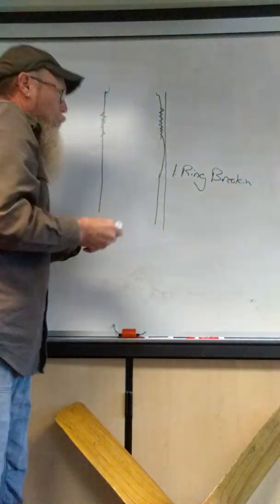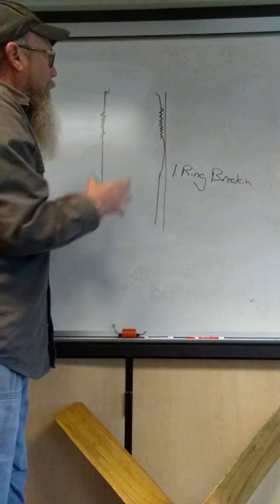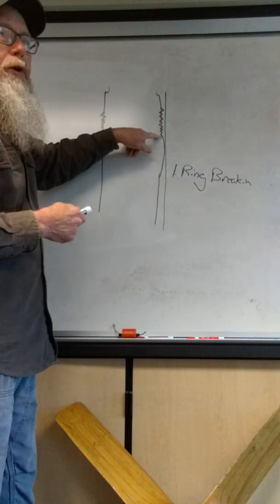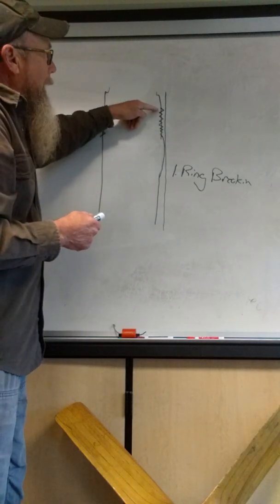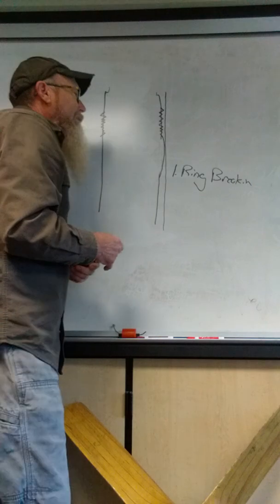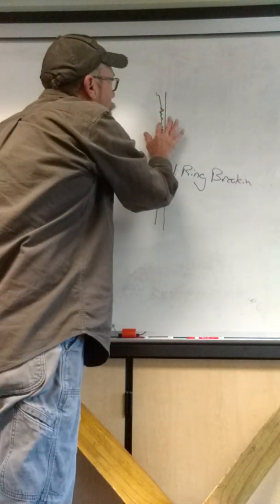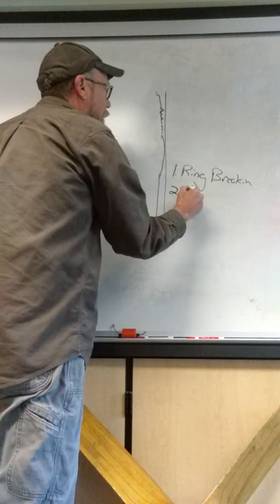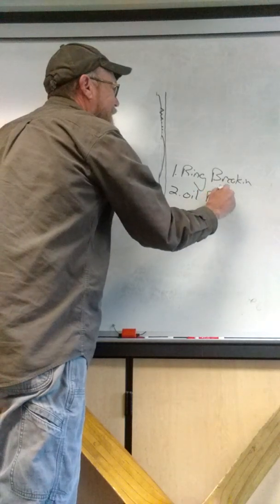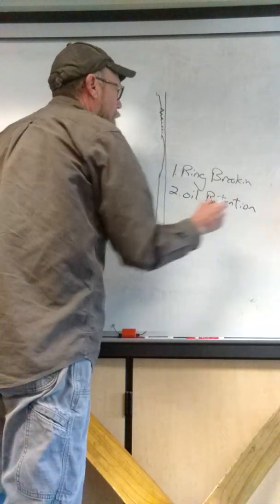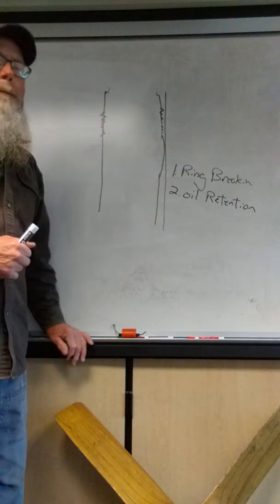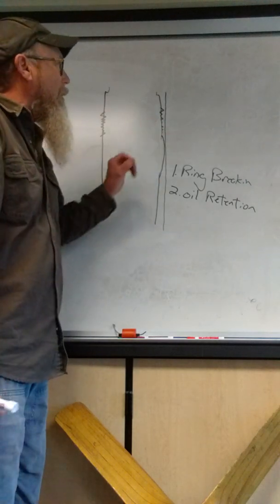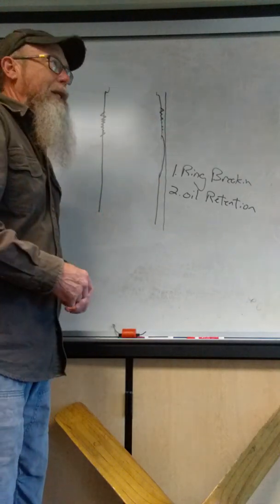So as the rings travel up and down the barrel, they're going to get perfectly seated into that cylinder wall, wearing on these little mountains in here. And so it's a 50 micron scratch that we're putting on this barrel for that purpose of ring seating. After the rings have seated in and the little mountains are basically worn down, then we're left with the valleys. And the valleys provide for oil retention. Because you've heard that you don't want metal to metal contact in an engine, we have that film of oil, and it's those little valleys that help that oil to retain to that cylinder wall.